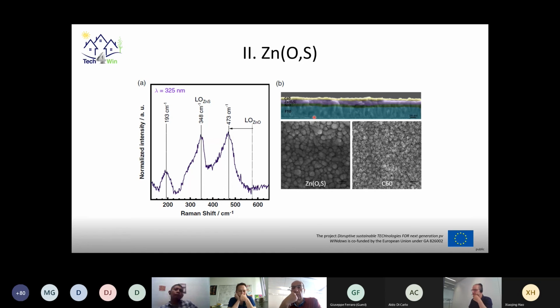You also see some SEM pictures, cross-section and top view. In the cross-section, you see that all the layers are well defined and quite smooth. In the top view for the zinc oxysulfide, you see some nano-sized clusters, kind of. But you also see a very compact layer, so that seems to be quite good. And the C60 seems to be quite porous. So that could probably be optimized and even maybe thinned down if we think about the C60 absorption that we have for the moment. So there's room for improvement, but it doesn't look too bad.